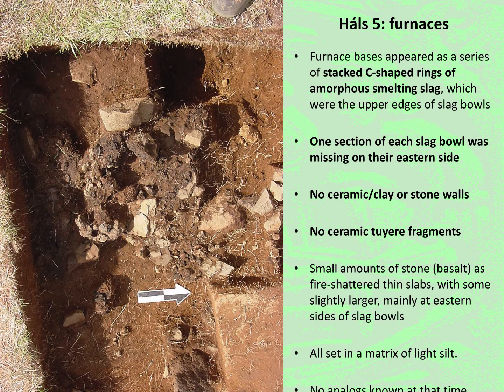There were a number of slag bowls found in place in the base of the furnaces, which would have marked the last use of iron smelting on site. There was also very limited tap slag recovered. The furnace bases were broken away to the east-hand side, which suggests a bottom extraction of those final blooms.